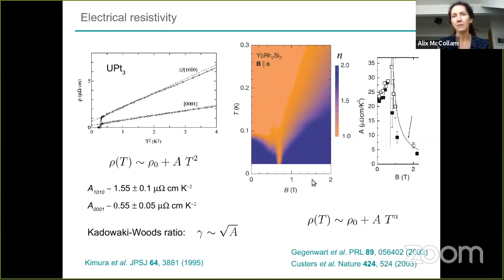On the other hand, ytterbium rhodium 2 silicon 2, this is the very famous phase diagram of ytterbium rhodium 2 silicon 2. This is not everywhere a Fermi liquid, so this is temperature versus magnetic field. And this color coding gives you the coefficient here. So here, instead of just 2, this is some other coefficient. In the region where this is dark blue, this is indeed a Fermi liquid. And in this region, the A coefficient is enormous. So this is A coefficient of 20, 22 at low temperature in these regions.